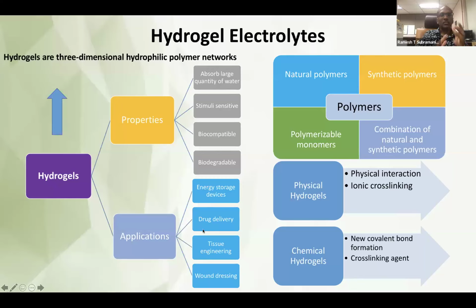Okay, next, when we talk about polymer electrolytes, like I mentioned earlier, the contact is always the main problem because of the nature of the materials. So when we produce hydrogel electrolytes, they become more like a double-sided tape where they can stick very well with the electrode materials. Hydrogels are three-dimensional hydrophilic polymer networks. We can make them by physical cross-linking, or we also can make them by chemical cross-linking. So they are called physical hydrogels and chemical hydrogels. For the chemical hydrogel, a new covalent bond will be formed.